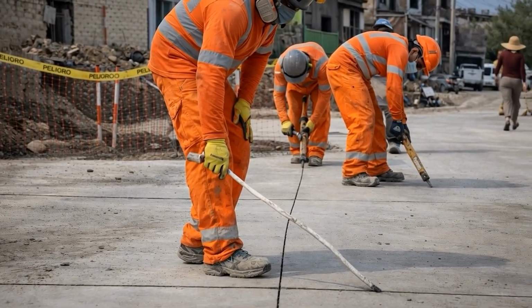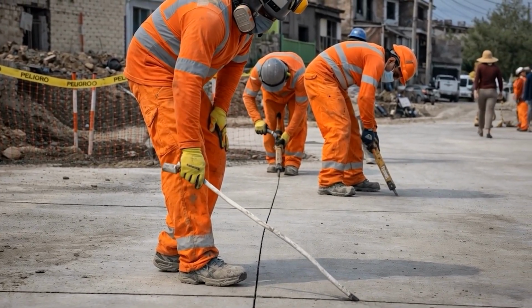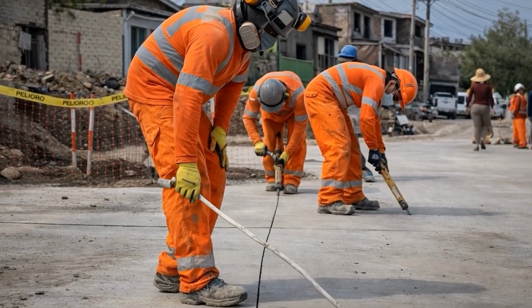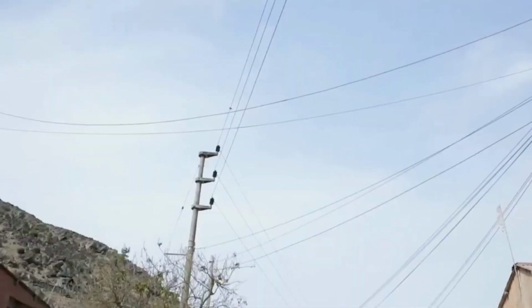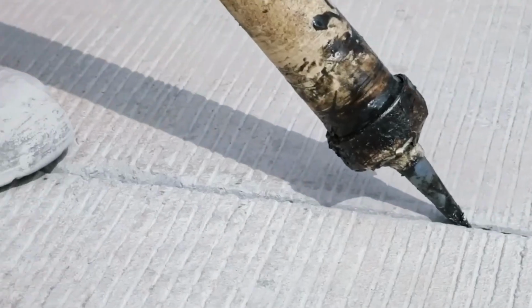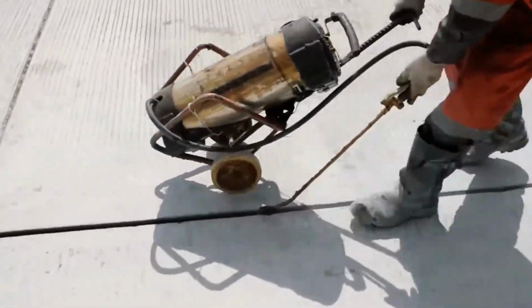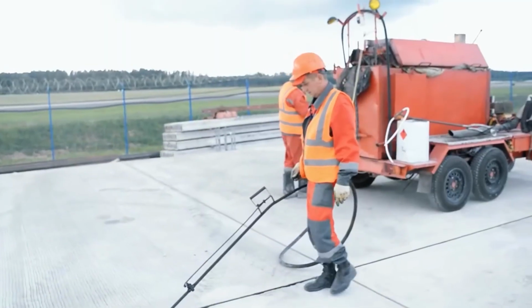After several more hours, the joints are thoroughly cleaned of dust and material residues. After that, a sealant is injected inside, most often polyurethane, silicone, or bitumen-based. It protects the joints from the penetration of water, dirt, and fine particles. Without such a layer, moisture could seep inside, destroying the concrete and the road base from below.